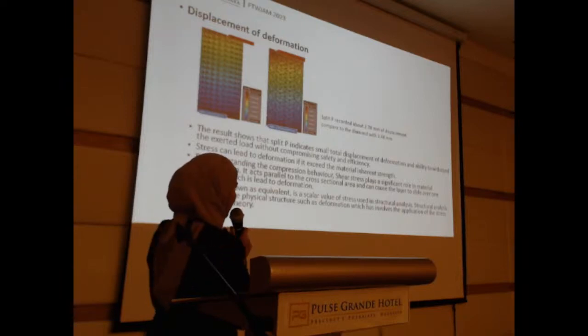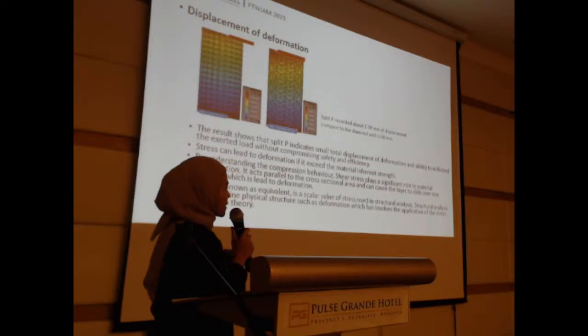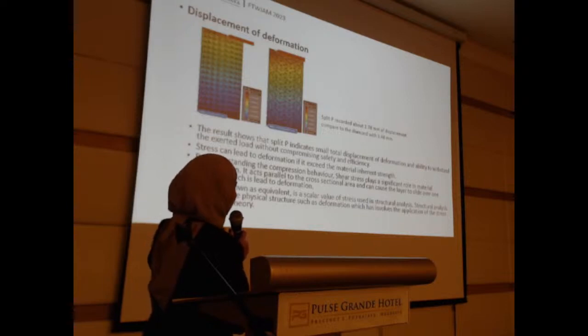Okay, displacement of deformation. Split P records about 2.7 mm of displacement compared to diamond with 3.48 mm. The result shows that split P indicates a smaller amount of total displacement of deformation, and split P has the ability to withstand the exerted load without compromising safety and efficiency. Stress can lead to deformation if it exceeds the material's inherent strength. By understanding the compression behavior, shear stress plays a significant role in material deformation parallel to the cross-section area and can cause one layer to slide over another, which leads to deformation.